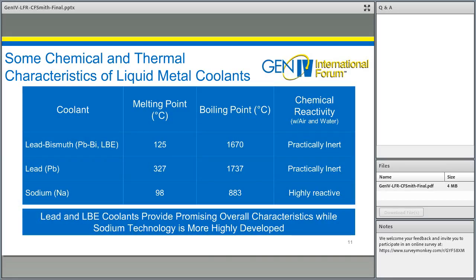This slide provides a few comparative details for selected liquid metal coolants. The first is lead bismuth. This is a lead-based coolant for some LFR designs, then lead, and then sodium. Lead bismuth, which is also referred to as LBE, or lead bismuth eutectic, has a melting point of 125 degrees centigrade and a boiling point of 1,670. Pure lead has both a higher melting point of 327 centigrade and a boiling point of 1,737 degrees.